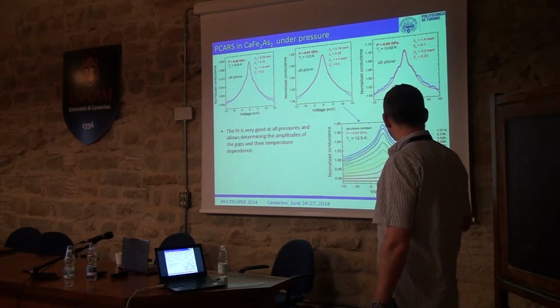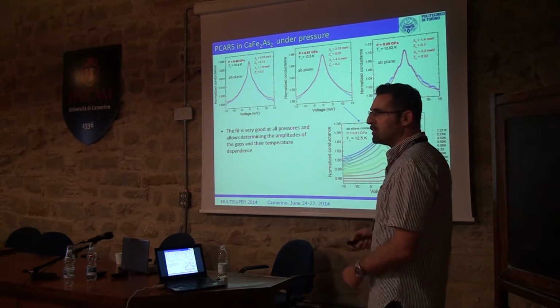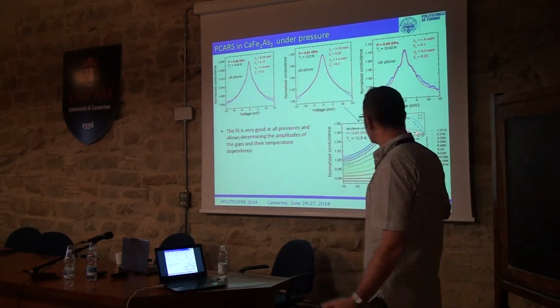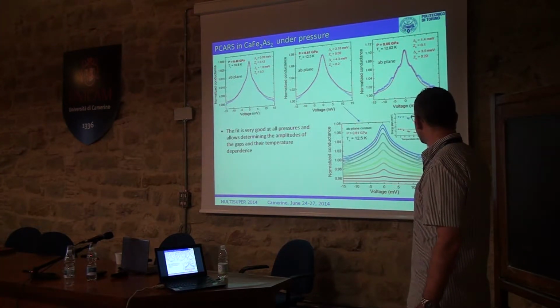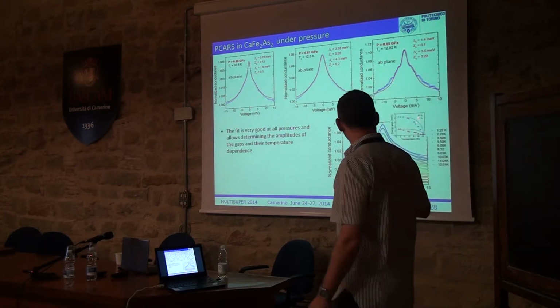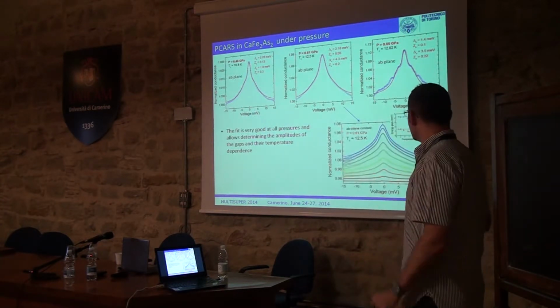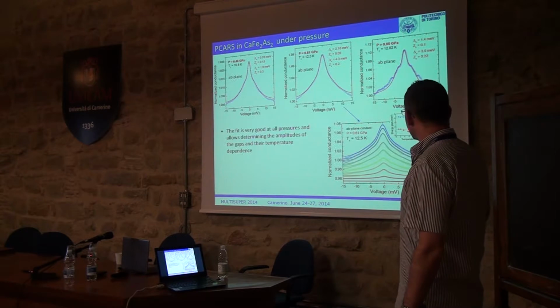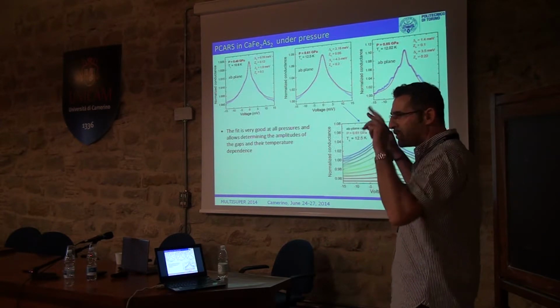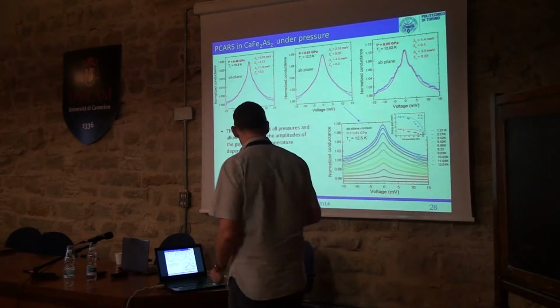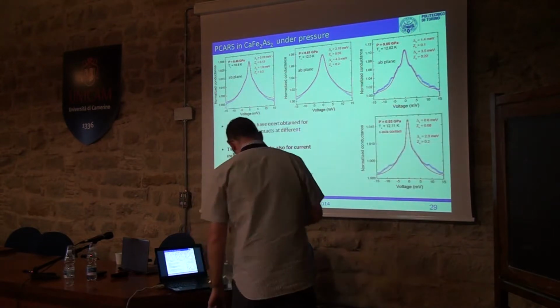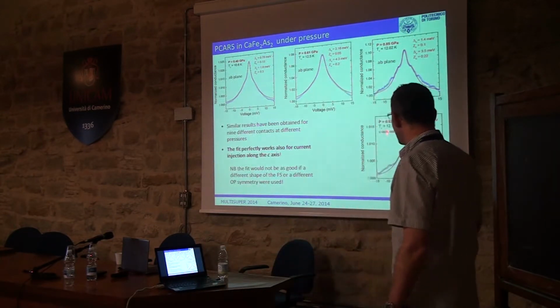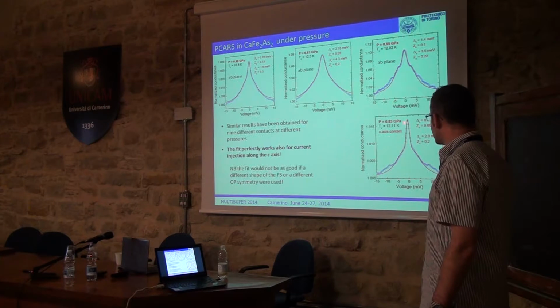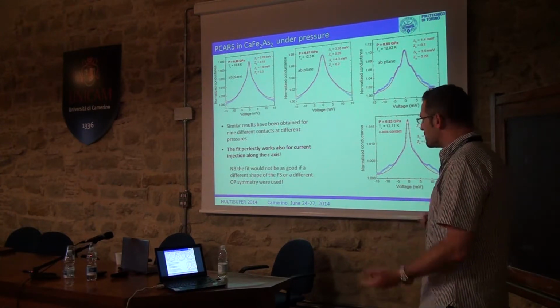It is also possible to determine the temperature dependence in particularly happy cases. Okay, here you see that these are the gaps. I would not squeeze this really because I don't have a very good evaluation yet of the uncertainty, but it seems that the gaps are both depressed below the so-called BCS-like behavior. And especially, the fit works also for C-axis injection. And this is very important because it's a proof of the internal consistency.